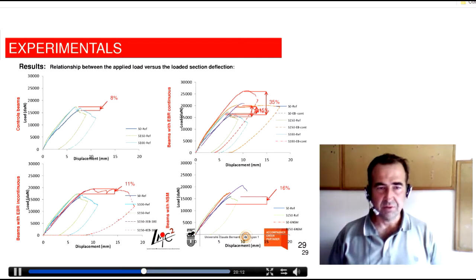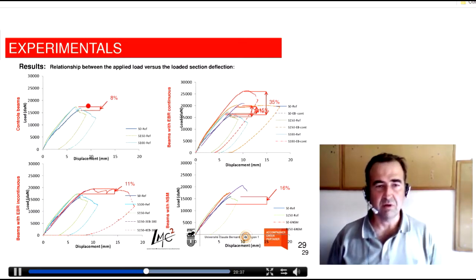So as a result, if we compare the reference one and the strengthened one, what we can observe is that if we have continuous strengthening, the increase in strength is very interesting, about 30%. But if this continuous strengthening is used with a very light, only one layer, the amount of increase in ratio is very low.